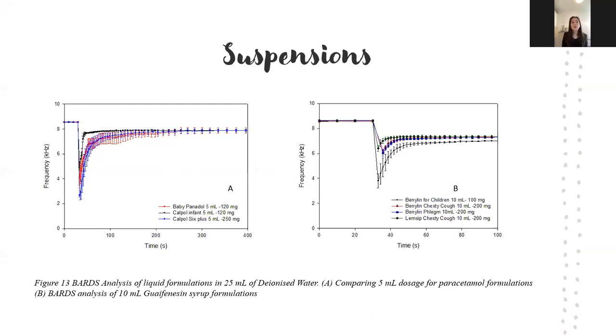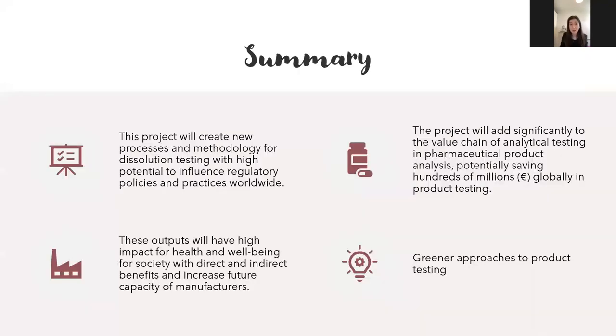It's interesting to note that the Baby Panadol performs almost identically to the Calpol 6 Plus, despite the difference in dosage. And you can see on our right, there's a smaller dosage in the Benylin for children of Guaifenesin, and Lemsip produces the most amount of gas. And there's an identical spectra, the chesty cough and phlegm from Benylin, as they're the exact same formulation with the same APIs, just marketed under different names.